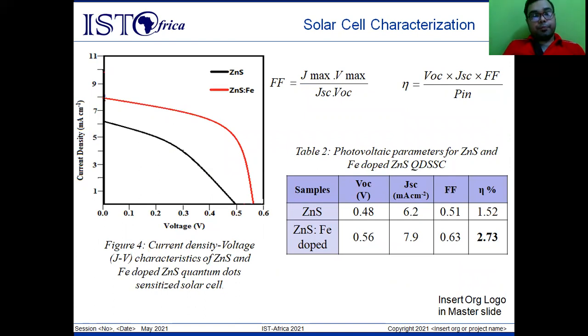Figure 4 shows the current density versus voltage characteristic obtained for the undoped as well as the iron doped zinc sulfide quantum dots based solar cell. So we can actually see from the curve that there is an increase on doping. The red curve indicates the doped, while the black curve indicates the undoped characteristic. Now, from this curve, we have determined the solar cell operating parameters, which are the fill factor and efficiency, the two important parameters, by using these formulas provided here.